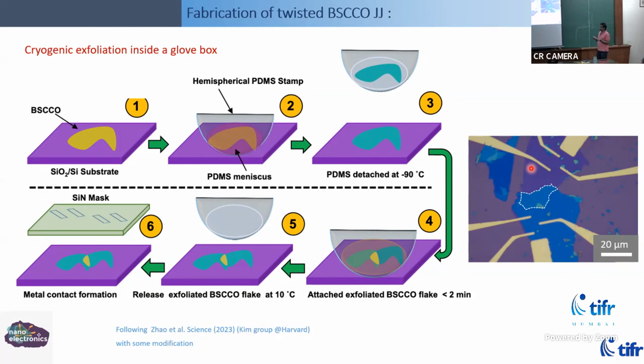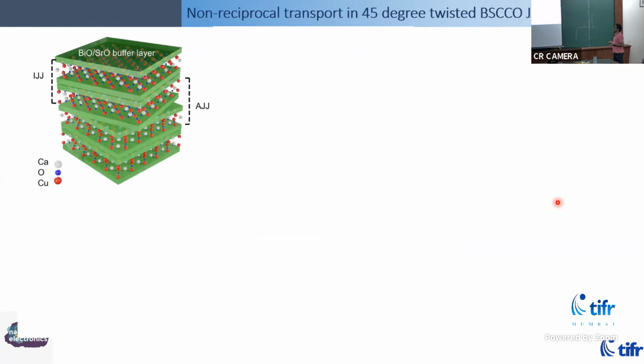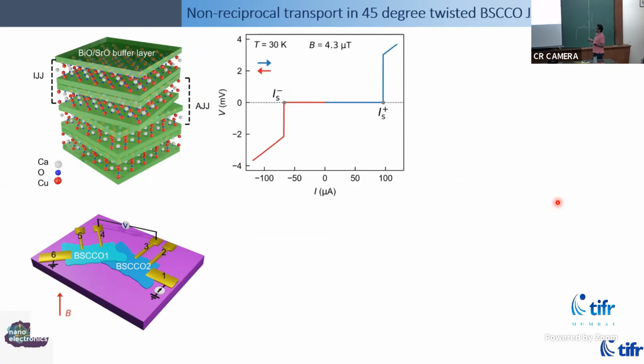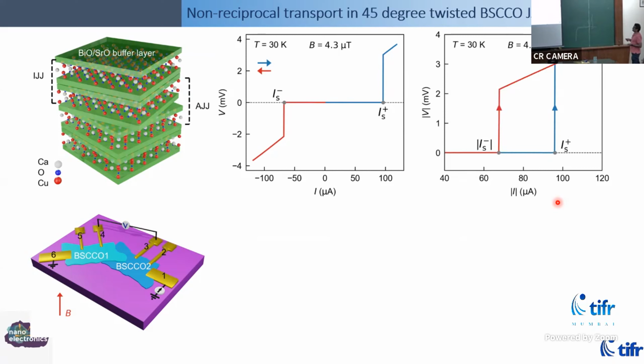These kinds of experiments, before this craziness of twisted 2D crystals, were actually unimaginable. People never thought of them, but once people started doing it with graphene, they realized that you could do it with other things as well. So one thing led to another. This is our device, and the current flows here in plane in two dimensions, and the same thing in the dark blue. But when it goes from here to here, it actually flows perpendicular because it has nowhere else to go. And that's the Josephson junction. This is a cartoon. When we measured the response of this device, we found a very large non-reciprocal response.